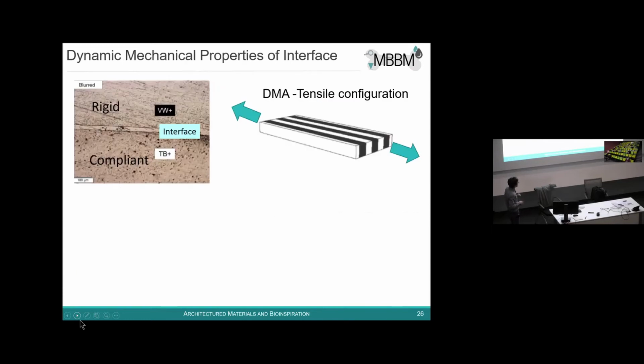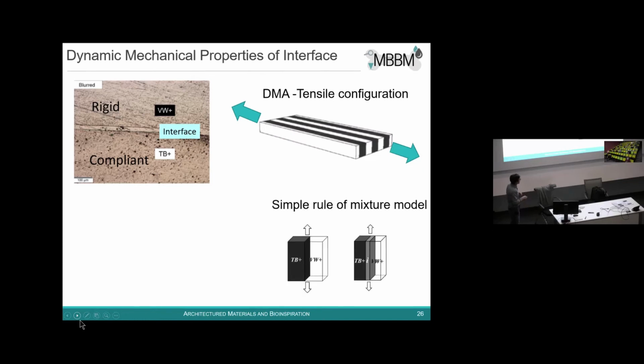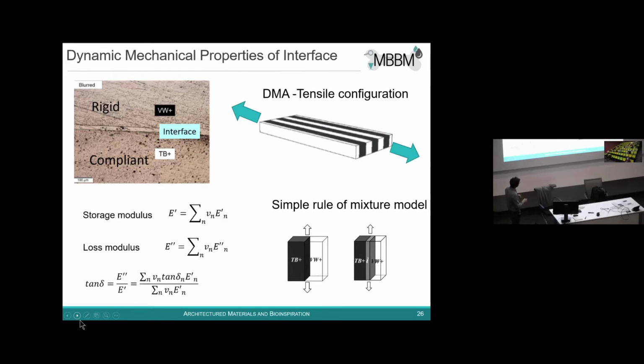And then we went a little bit further, and we designed other samples. So this is an optical picture of the interface between the rigid and the compliant polymers. And we now tested the samples in tension, not in 3-point bending, but in tension, still dynamic mechanical analysis, but in a tensile configuration, because in a tensile configuration, we could use a simple rule of mixture model to get the dynamic properties of the interface itself, which is not possible in 3-point bending, because it gets a little bit too complicated, especially for the loss properties. So we could then use a simple rule of mixture and come up with a model to predict the storage modulus, the loss modulus, and the tan delta of this.